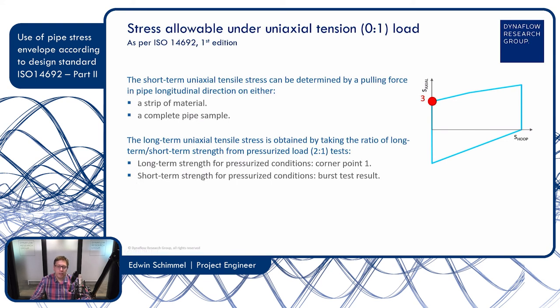So we pressurize the pipe to much higher pressure, 2 or maybe even 3 times the long-term pressure, and then, well, in the end it will burst, and that gives us the burst test pressure. And then the ratio between the long and the short-term pressure under this 2-to-1 load, so pressurized condition, the same ratio we apply to the short-term strength. And then we get the long-term uniaxial strength, and that's corner point 3. So that is the third out of 5 corner points that we need.